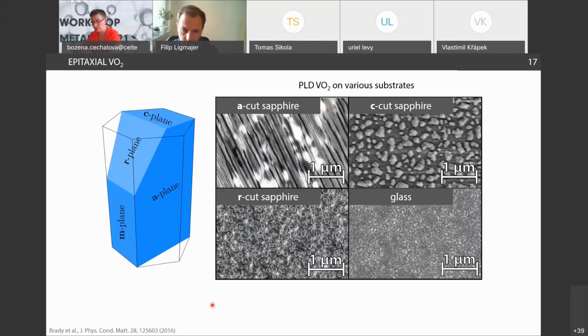Then what we did was a collaboration with the group of Richard Haglund from the United States. They were capable of fabricating really nice thin films of VO2. What they observed was that, based on a different cut of their sapphire substrate, because this is a sapphire crystal and you can cut it in different planes, traditionally denoted as C, A, M, or R, if you deposit your VO2, for example, on A-cut sapphire, you will get these nice nanobeams of VO2, unlike the conventional case where you have a typically polycrystalline VO2 thin film.